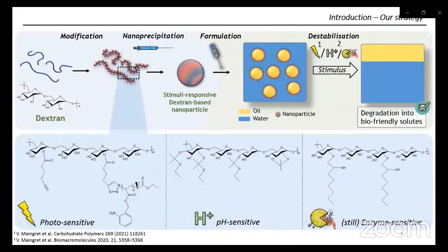More specifically about the modification step, in the first case, lower left, we grafted a photosensitive hydrophobic polymer, poly(nitrophenyl acrylate). In the second case, we grafted acetals, which bring the pH sensitivity. And finally, in the third case, we grafted alkyne chains in a lower amount, which keeps the enzyme sensitivity properties of dextran available.